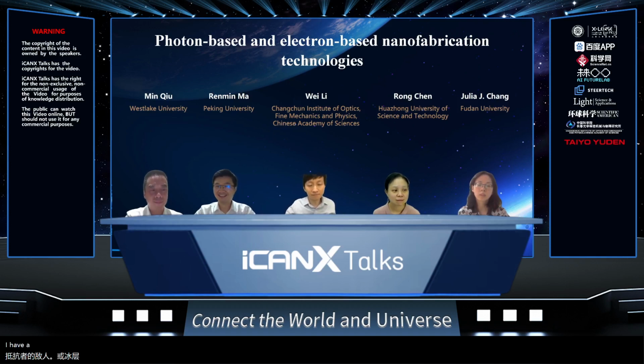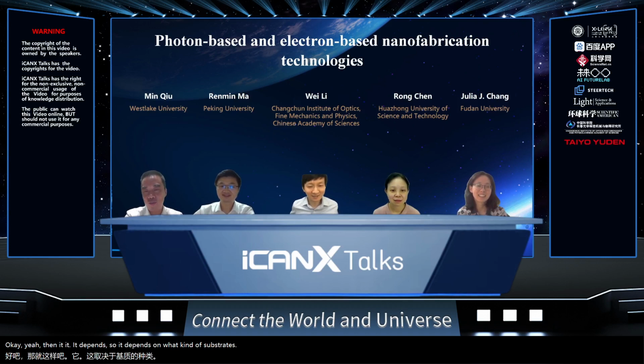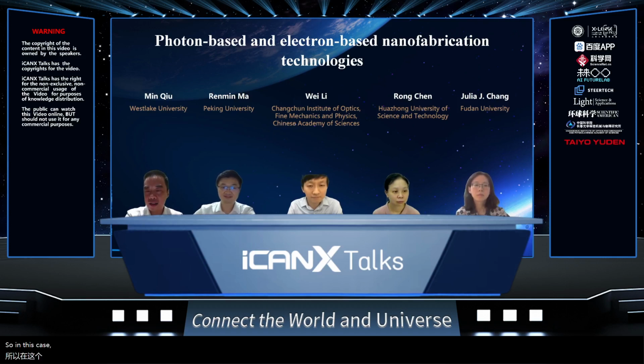Have a nice weekend. Okay, yeah, it depends. So it depends on what kind of substrate. For example, if you have 2D materials in our experiments or perovskite, if you have electrons directly interact with this substrate, they will truly destroy the substrate. So in this case, ice will be a protecting layer for e-beam lithography. On the other hand, electrons can penetrate into ice fairly easily, depends on the energy.